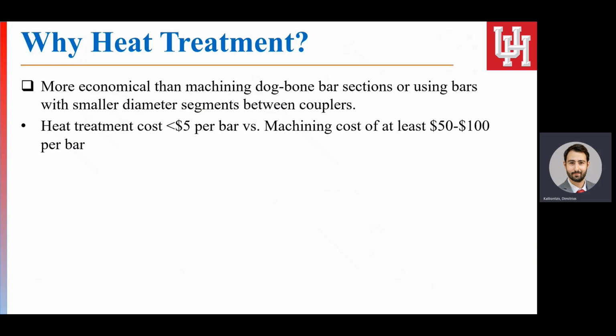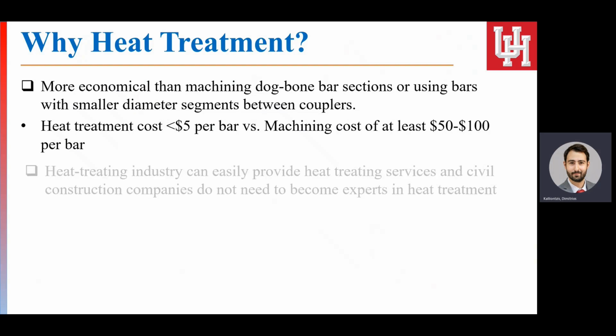So the question now is, why should we use heat treatment? Because in the past there have been other methods of localizing the energy dissipation in bars, such as machining to create a dog bone bar section, or using bars with smaller diameter between segments that would be established through the use of mechanical couplers. First of all, heat treatment has a much lower cost that, based on our experience, is about or less than $5 per bar, while machining the bars would probably end up being $50 to $100 per bar, and using couplers could also increase the cost further.